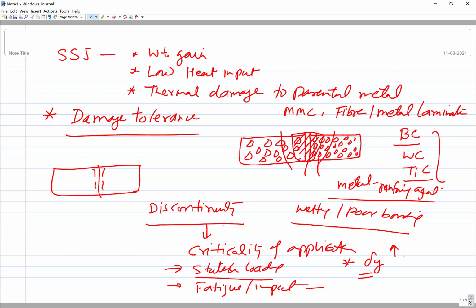On the other hand, if the metal is of low yield strength and good ductility, localized yielding will easily take place, and that in turn will reduce the stress concentration caused by the discontinuities, so their severity will be reduced. So the higher the yield strength, sigma y, the greater the issues related to the discontinuities. Okay, this is one thing.